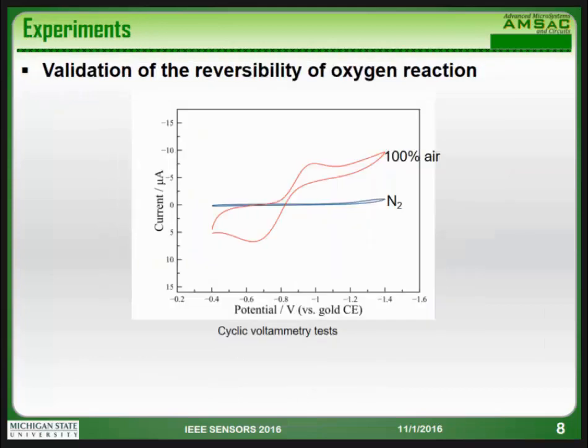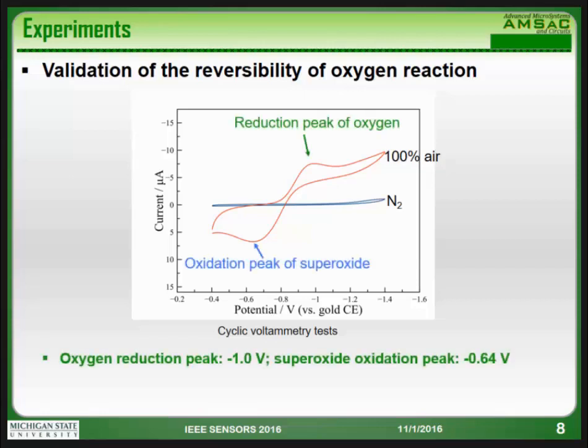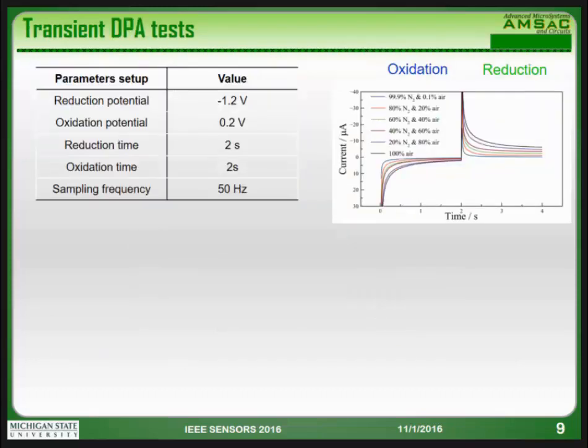Before our test, we want to validate whether the oxygen reaction is reversible in ionic liquid. So we conducted the cyclic voltammetry test, and from this result we observe the reduction peak of oxygen here and the oxidation peak of superoxide here. From this result, we concluded that the reaction of oxygen is reversible. So we performed the transient DPA test next. We tested six samples.